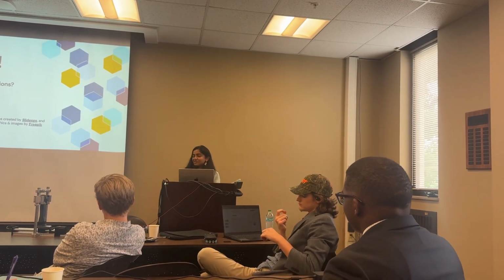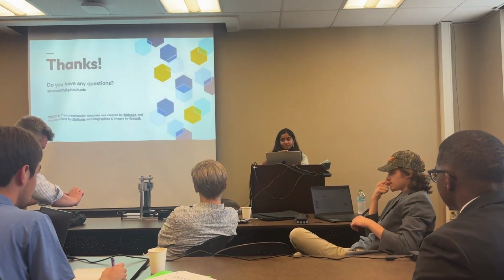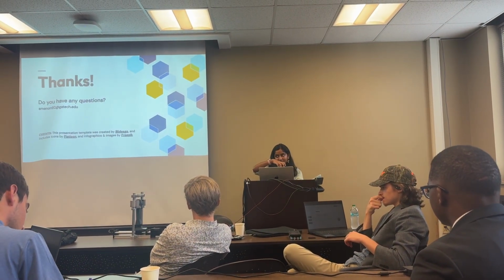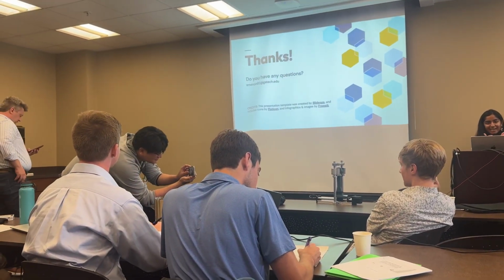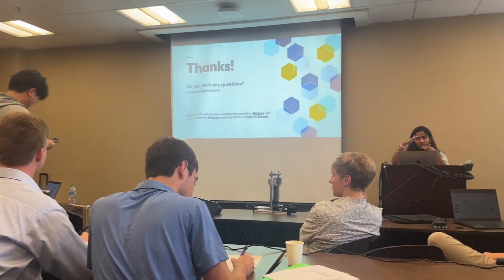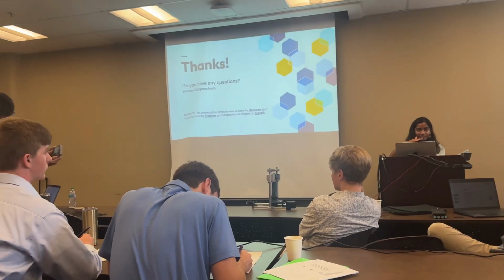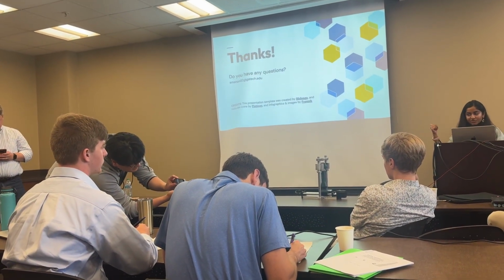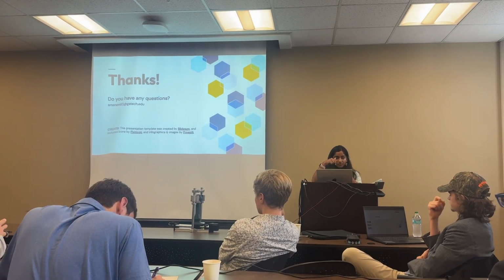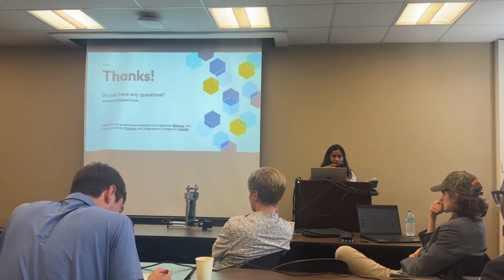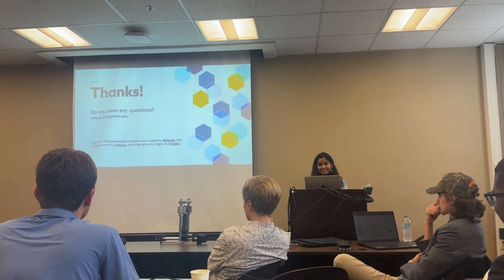So on our, I wish I had a picture of it, but for our stacking stage, the stage that our chip is actually sitting on has a motor that can control the rotation of it, and that has a very high precision. So once we pick up the first half of the flake, you rotate that stage by 1.1 degrees, and then you'll realign like I showed in that picture before, where you're trying to match where your hBN is and where that first flake of graphene falls on it to where your second flake of graphene is, and then you'll lower down and pick it up. Thank you.